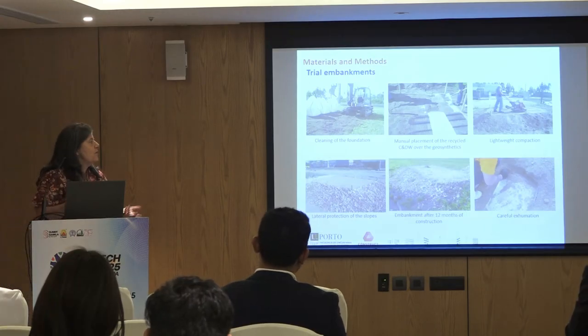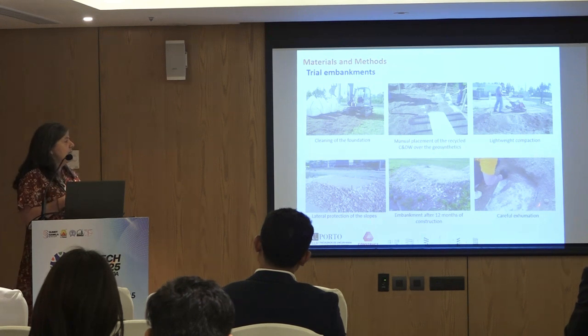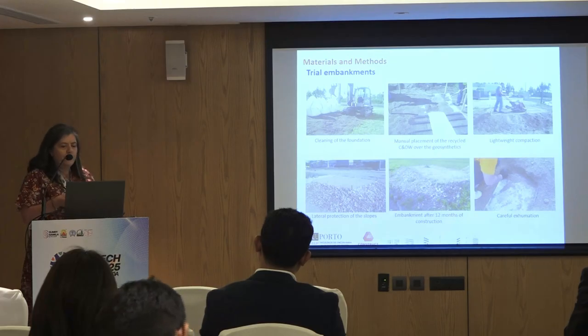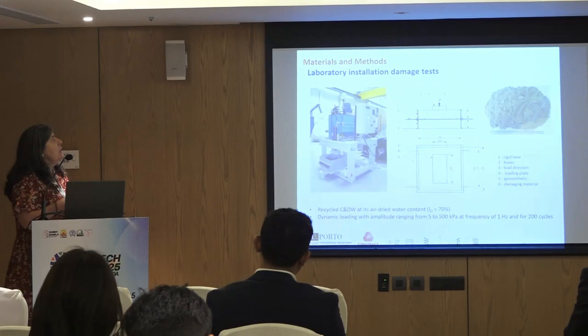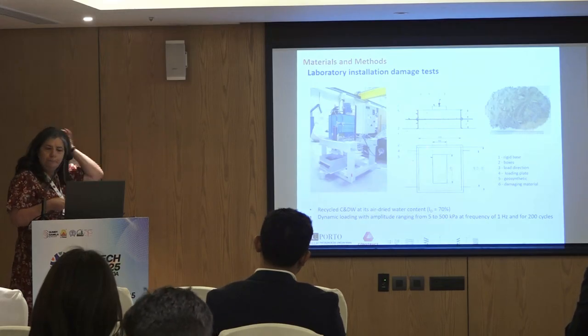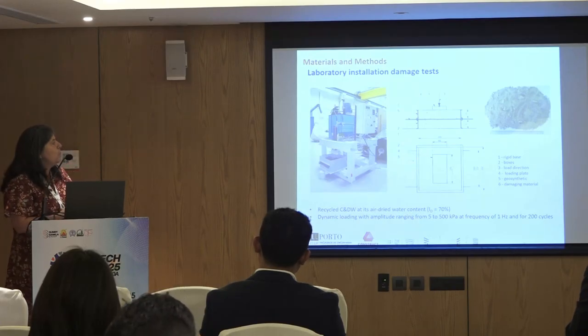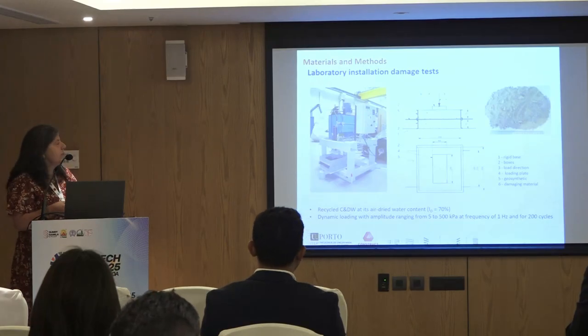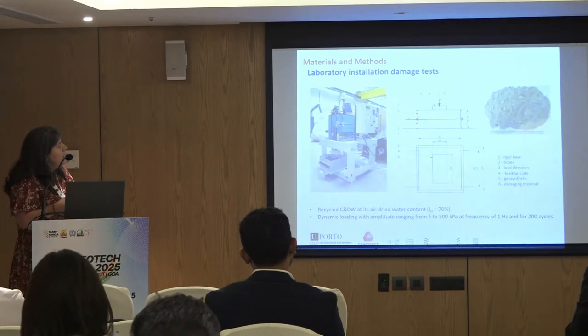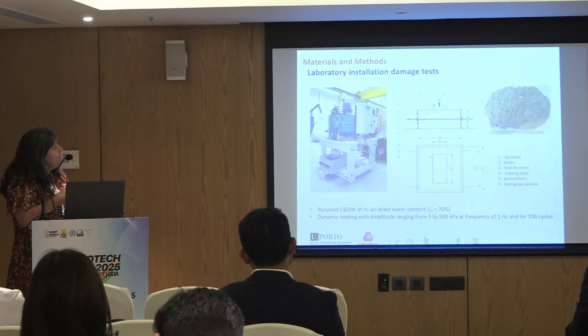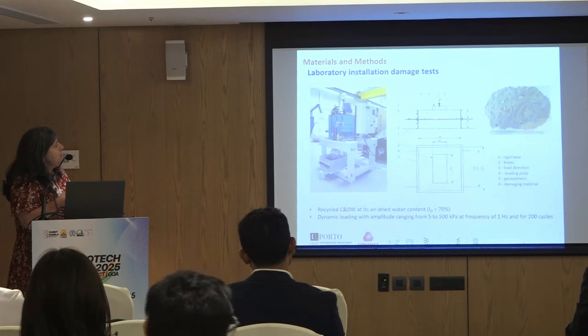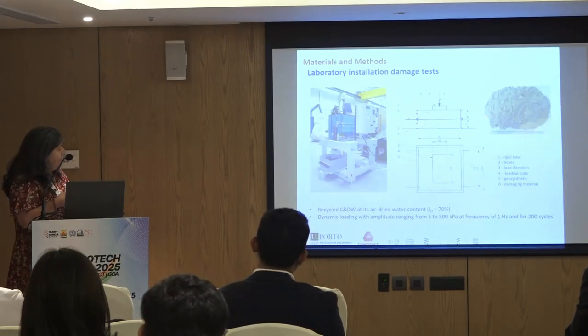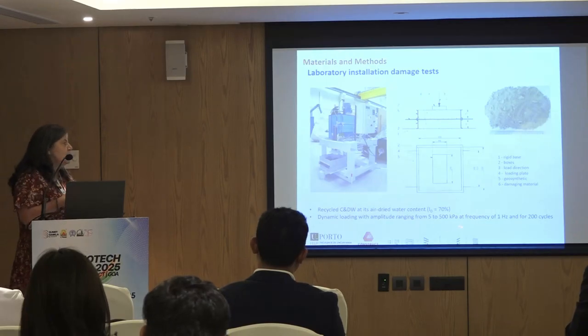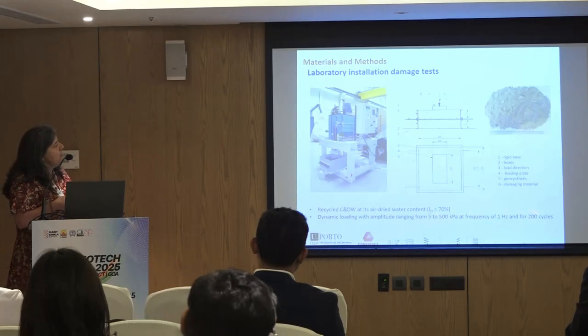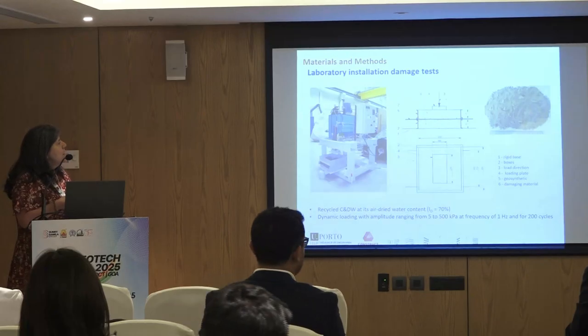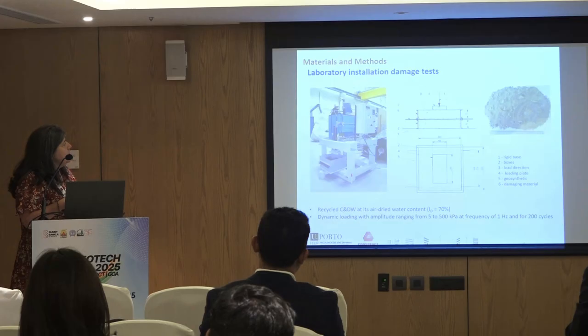After 6, 12, and 24 months of the embankments' construction, the samples were carefully exhumed to avoid any kind of additional damage. Laboratory installation damage tests were also carried out. We used a laboratory prototype developed at our University of Porto, composed of a steel box, 300 millimeters square. This box is filled, in this case, with the recycled material, and the geosynthetic is placed at the middle of the height. Dynamic loading with amplitude ranging from 5 to 500 kilopascal at this frequency, and for 200 cycles, was induced in these materials.